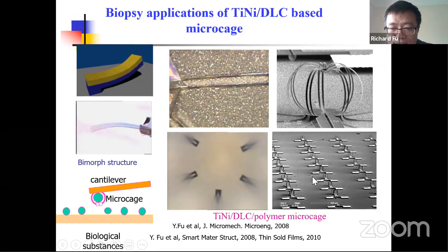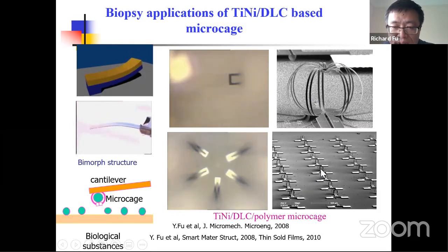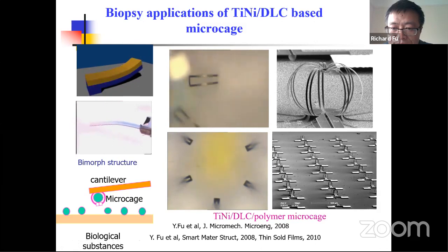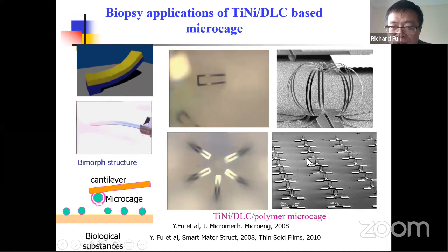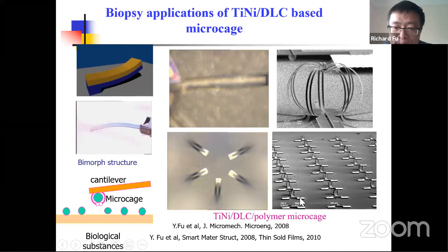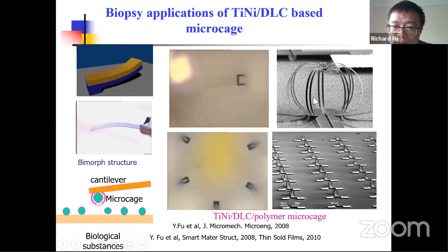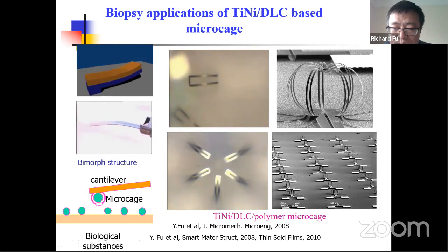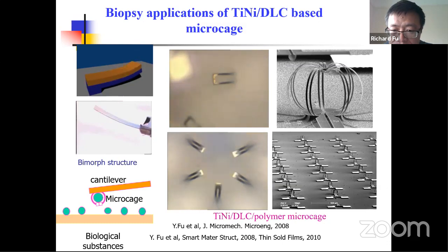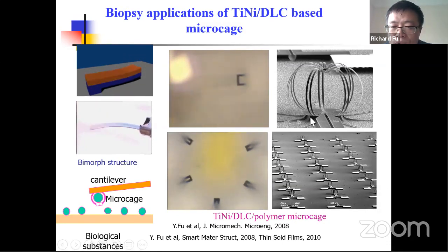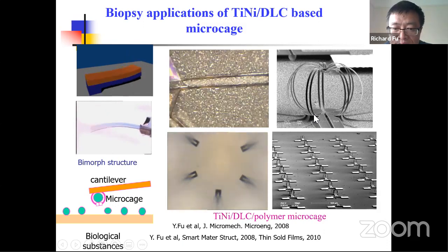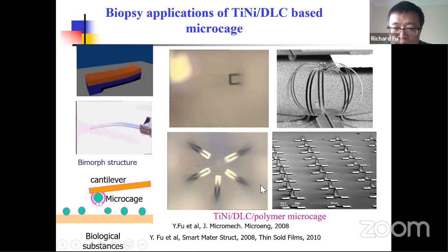For our operation, the temperature is still a little bit high, because we want the operation temperature to be as low as possible, for example room temperature. For this case, what we can do is integrate polymer inside. As we know, if we have polymer integrated with this kind of multiple-layer structure, the polymer has a very large thermal expansion coefficient. It will bend the structure significantly, and it also has a very different Young's modulus compared to other films. So if we combine the three-layer structure, it will function much better.